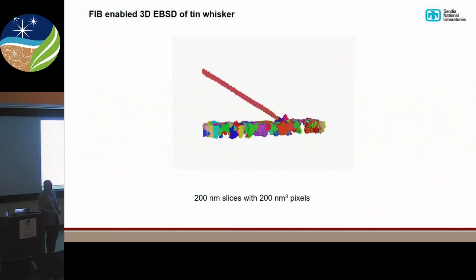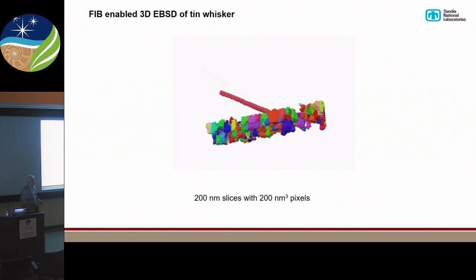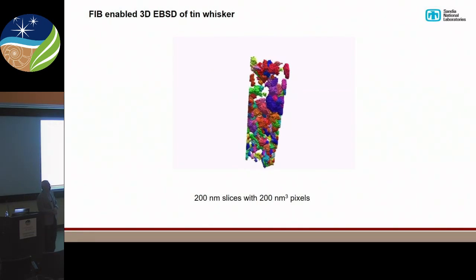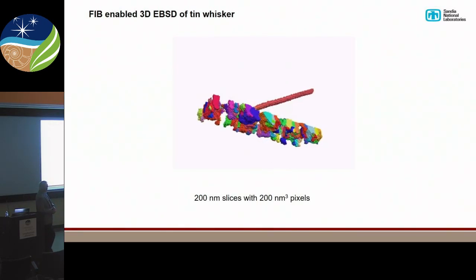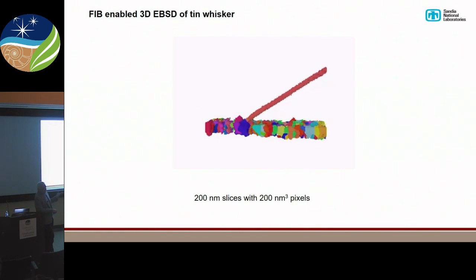The other thing we can do is we can start looking at things in 3D. So if you have a FIB and you have an EBSD on there, you can do this: slice, an image, slice, an image, slice, an image. And so this is basically 200 slices through one of those tin whiskers, about a 200 nanometer cube pixel. And if Microsoft helps me, we can actually then take that and rotate it around. You can take a good look at the structure and how that whisker has grown out of the substrate tin.